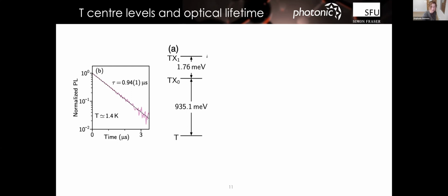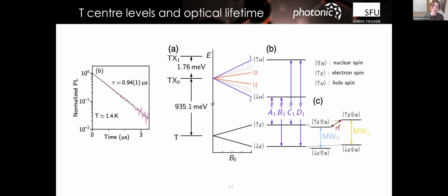In terms of the spin structure, it gets a little messy because there's a lot of orientations. What you get is all these extra nuclear spins that you can play with reliably every single time you make this center, if you're implanting carbon-13 in particular. But that additional structure has the cost of having different orientations. If you're on an off-axis degeneracy when you're applying a magnetic field, you can see up to 12 different orientations in PL, and actually that's 24 different orientations under inversion symmetry. So you have quite a bit of space there.